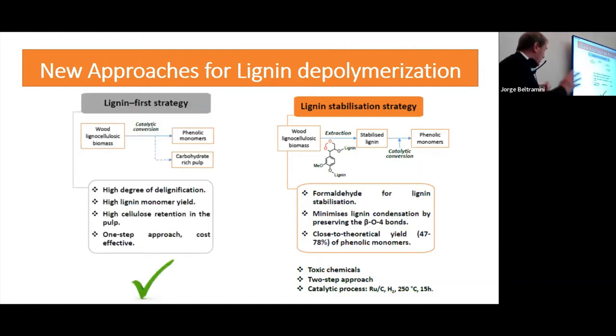So the idea here was to create a strategy with the principle of partial oxidation. And what we started working on is what we call the lignin-first strategy. It is one catalytic step, one reaction step, where we separate the phenolic compounds, the lignin monomers, from the carbohydrate fraction. We don't use hydrogen as a gas; we use air, we use oxygen from the air. And still, we have a very high monomer yield. We can retain the cellulose and the hemicellulose, which can then be fermented and converted into sugar. And the more important thing, what industry likes, is that it is only a one-step approach.